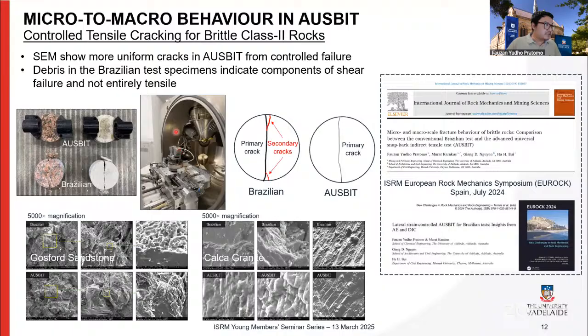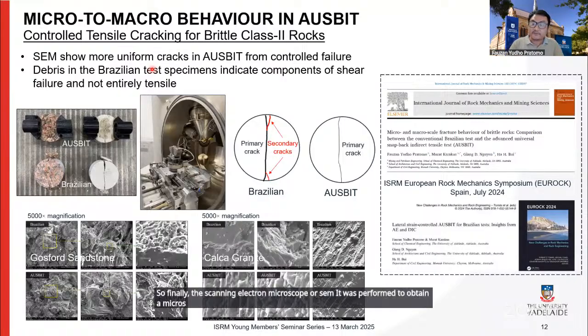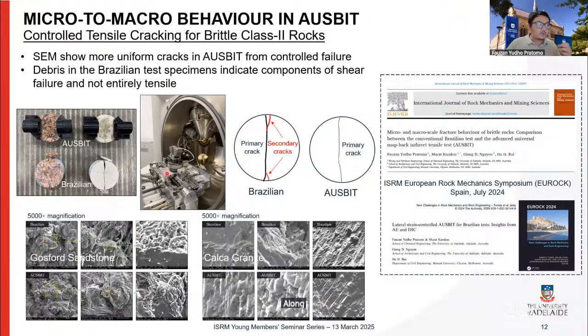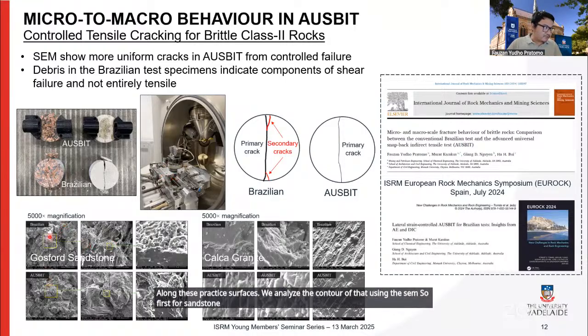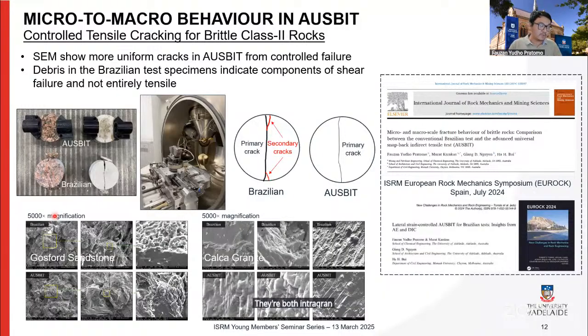So finally, the scanning electron microscope, or SEM, was performed to obtain a microscale perspective of the fracture surfaces. Along these fracture surfaces, we analyzed the contour using the SEM. First, for sandstone, between Brazilian and AUSBIT at 5,000 times magnification, there were no major differences between the two tests. They're both intergranular cracks dominantly being identified.